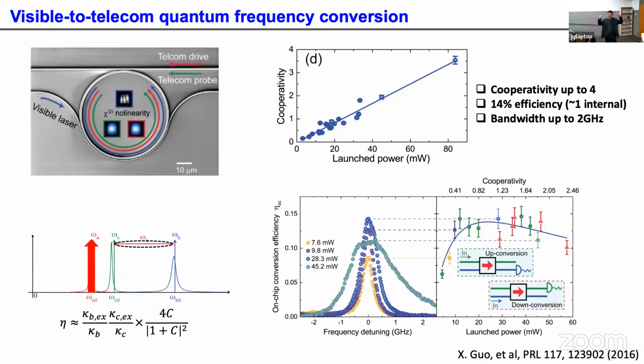If your two resonant modes are fully overcoupled, that means the intrinsic loss does not play a role in your conversion system, and you would have 100% conversion efficiency. Here in our two modes, they are both undercoupled by about 3 to 4 dB, and that's why you get a total conversion efficiency of about 14%.